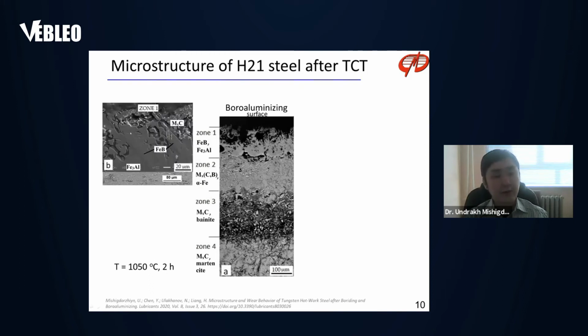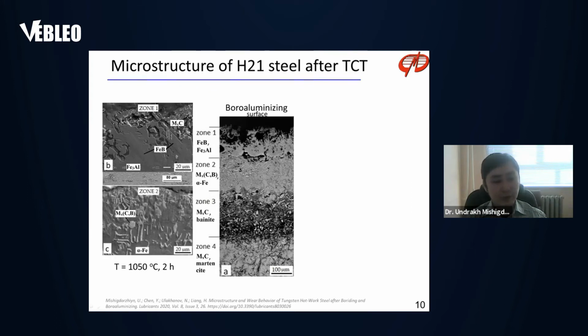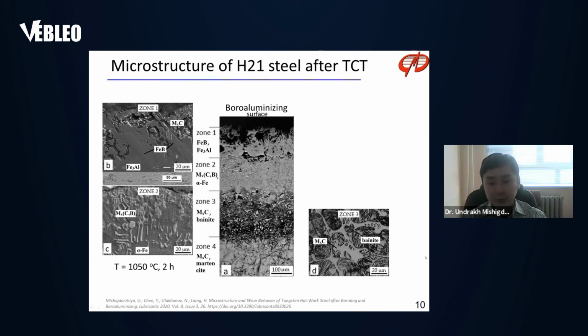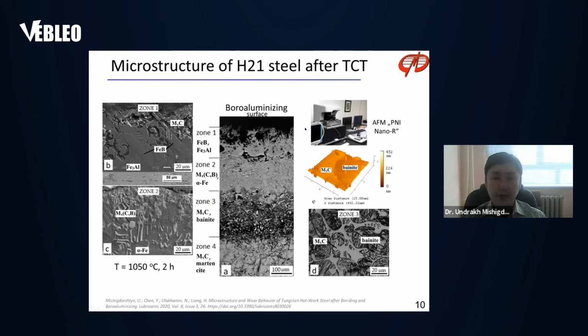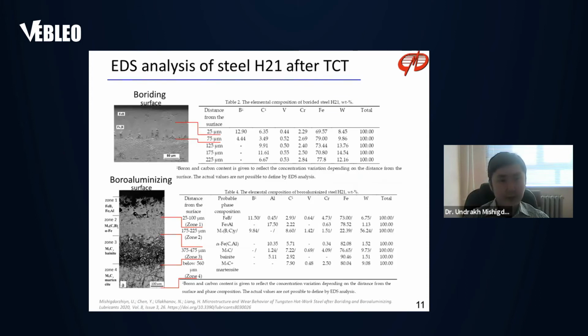Zone 1 contains ferrum boron needles, precipitation of carbides on top, and iron aluminide. Zone 2 contains elongated and small crystals of carboboride placed in a matrix of solid solution of aluminum in iron. The magnified picture of zone 3 revealed bainite surrounded by a net of carbide. And we also provided AFM analysis to obtain a 3D picture and to measure elastic moduli of the obtained layers.